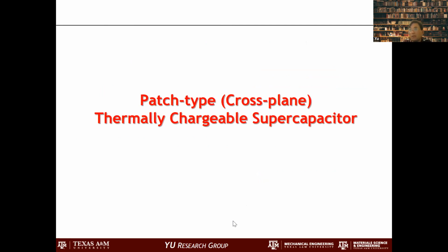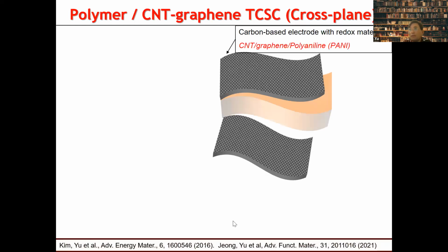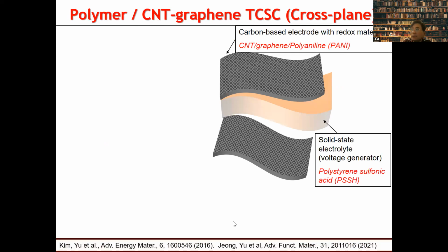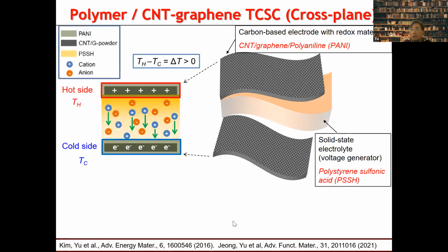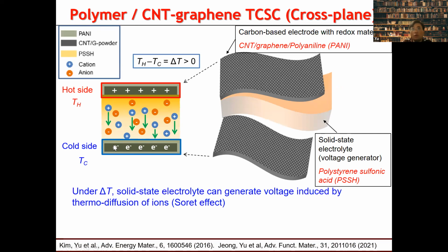So the first one is a patch type and cross-plane. We made this device using carbon nanotube and graphene powder with the polyaniline polymer, which is called a redox polymer, together with polyelectrolyte inside. And it's a capacitor like this. You do have the hot side electrode and cold side electrode, and this one contains a proton. And when the top side becomes hot, then the positive ion is moving. And then we do have ion accumulation, so we can store the energy.